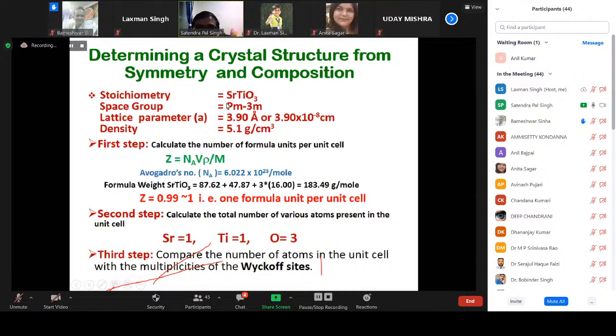So you have to know how many formula units there are, like strontium has one strontium, one titanium, O3. So how many of this formula unit exist in the unit cell? How can you determine that? Using the density, the volume, and the molecular weight, you can determine the Z value. So what is the number of formula units per unit cell? That is very important.